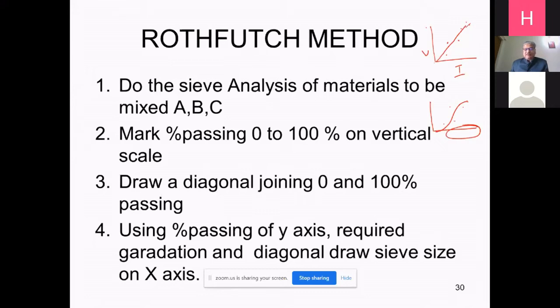these are the steps. Do the sieve analysis of the materials to be mixed, A, B, and C. After that, mark percent passing 0 to 100 on the vertical scale: 0, 10, 20, 30, 40, 50, 60, 70, 80, 90, 100. So you have marked the vertical axis 0 to 100%. Now, without putting the actual values on this, you have to draw the curve. You have not even marked the x-axis, you have drawn the curve.